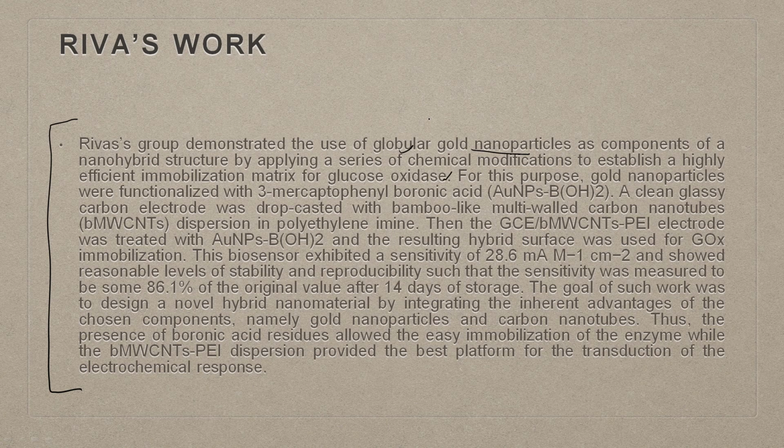So, this whole idea is putting more and more glucose oxidase, immobilizing them on the gold surface. For this purpose, gold nanoparticles were functionalized with 3-mercaptophenyl boronic acid. A clean glassy carbon electrode was drop casted with bamboo-like multi-walled carbon nanotube dispersion in polyethylenimine.